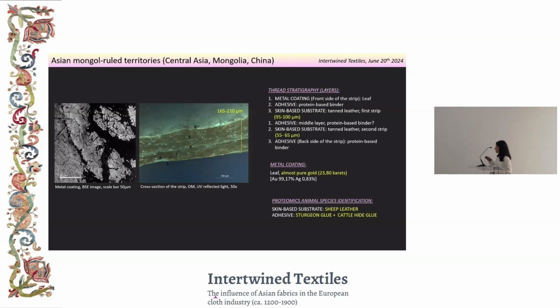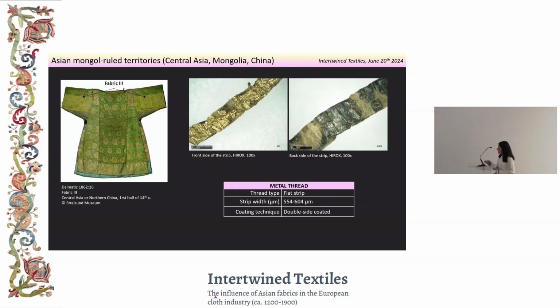And indeed, the thickness of the strip, this is one of the thickest that we have found, of 200 microns. The proteomics analysis helped us to identify for the first time the origin and animal species of the skin as well as of the adhesive. And we have found that they used sheep leather, and the adhesive was a mixture of sturgeon glue and cattle hide glue. In these other fabrics, also present in the dalmatic, the thread is a bit different.